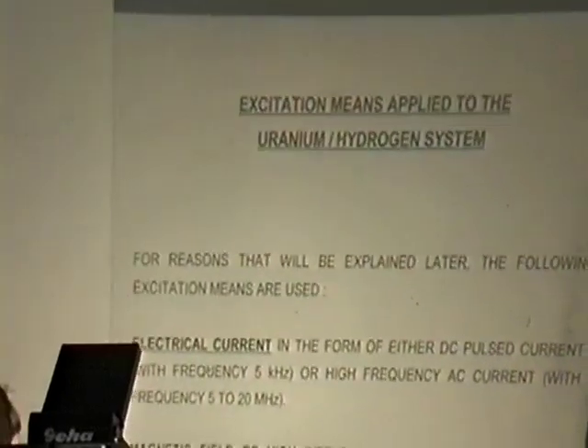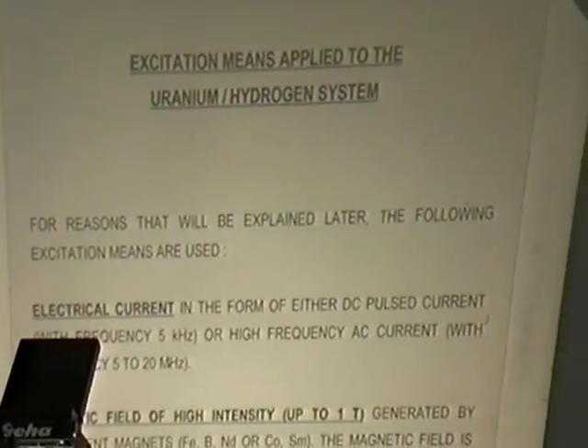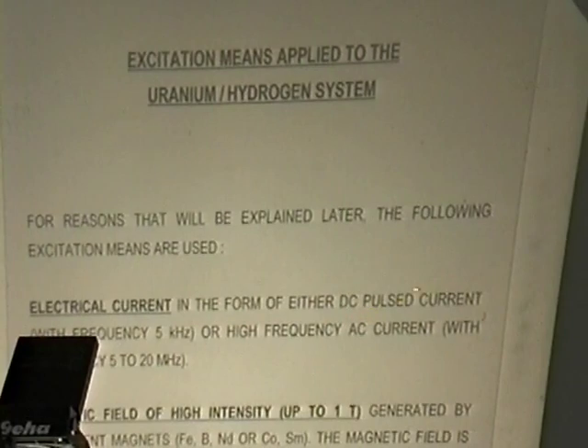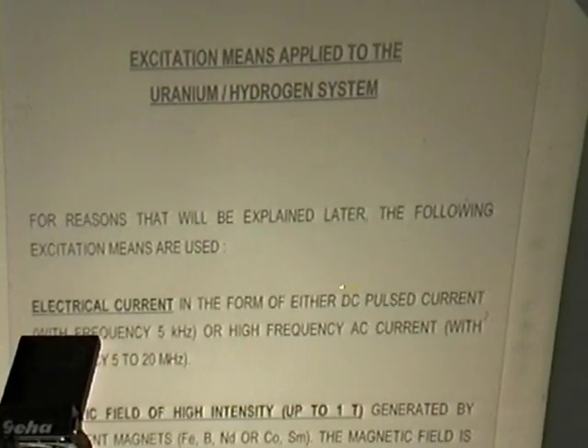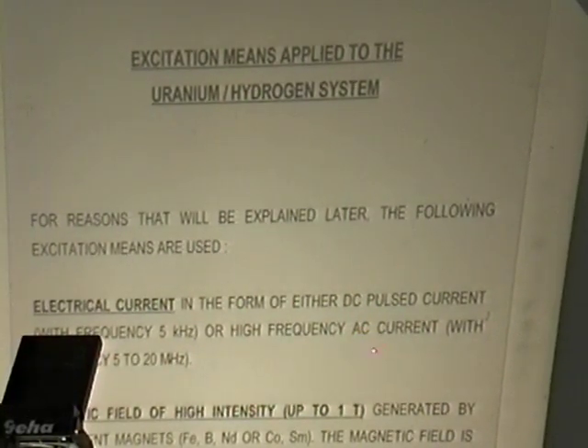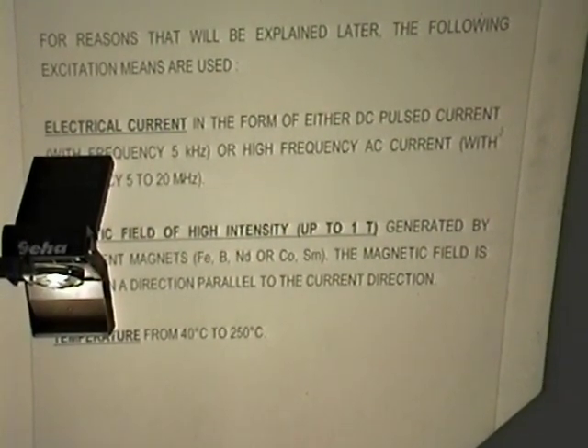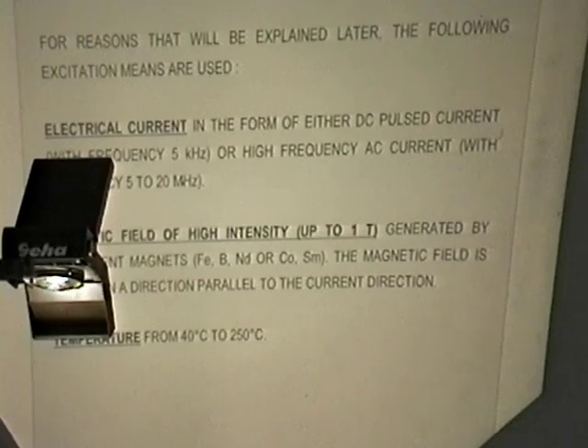The excitation means we applied to this system were the following: electrical current in the form of either DC pulse current with 5 kilohertz frequency or high frequency AC current with frequency up to 20 megahertz. And a magnetic field of high intensity up to 1 Tesla generated by permanent magnets, and this field is applied in a direction parallel to the current direction. The temperature was varied from 40 to 250 degrees C.